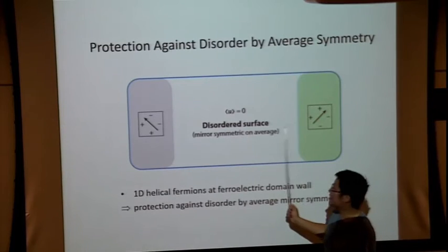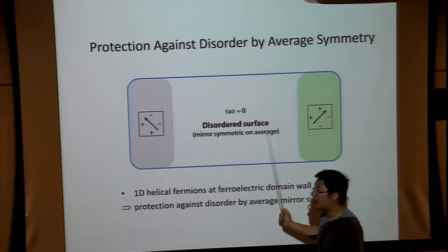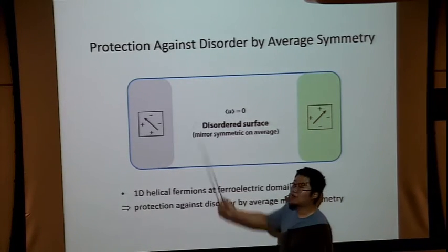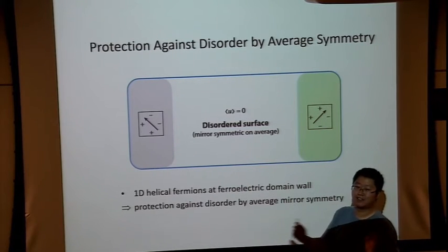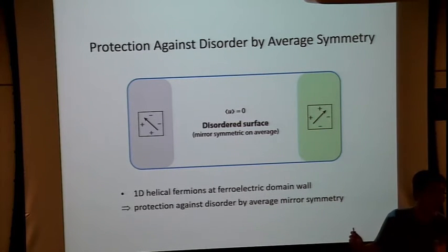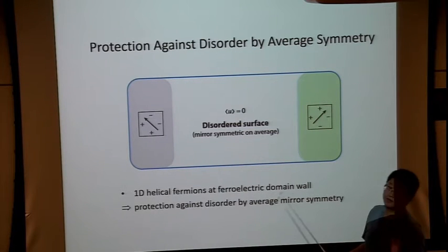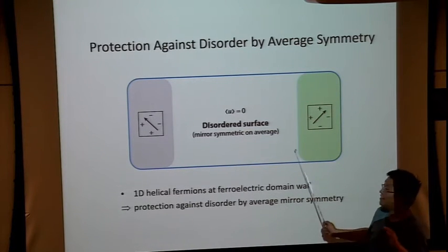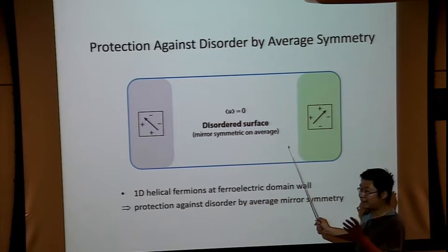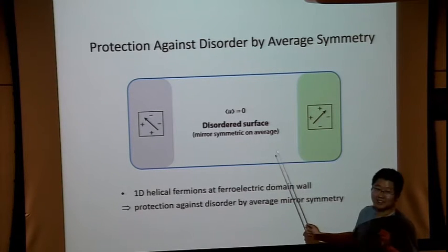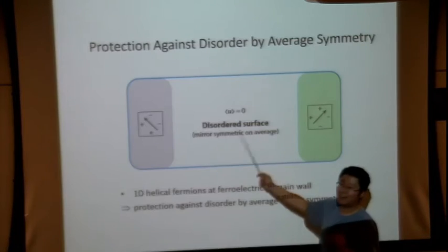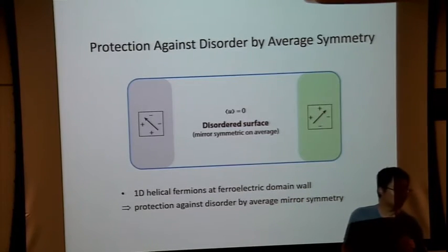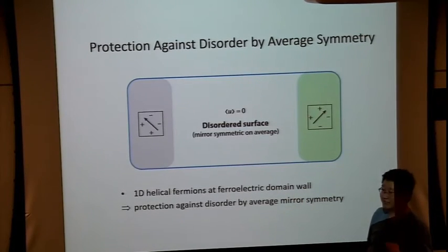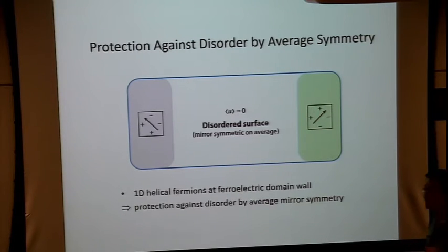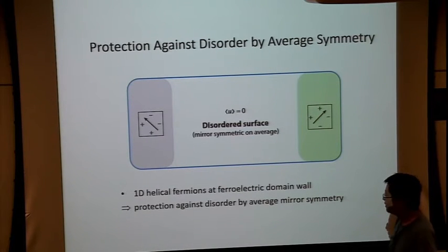Furthermore, we know that there's no way of splitting a helical edge state into two components while time reversal symmetry is present. So with time reversal symmetry, the non-magnetic disorder, no matter how strong it is, cannot localize the surface states, provided that mirror symmetry is on average present.